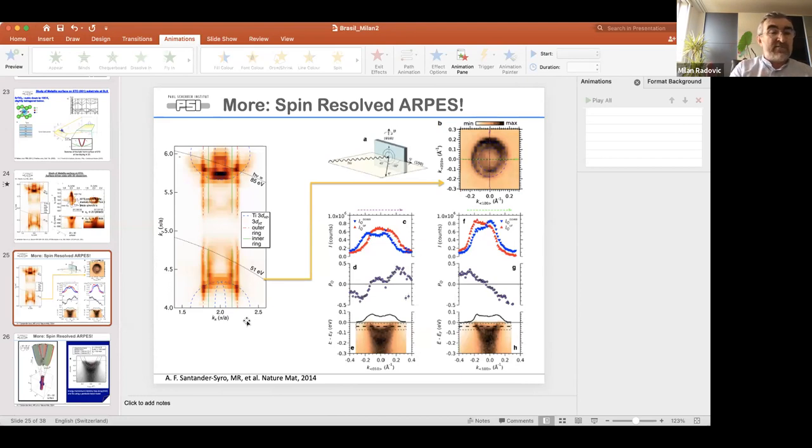For the STO and the films which we have, that can be achieved. For other systems, maybe it will be difficult. The second thing is, that means you have a large flux and long acquisition time, so beam damage can occur. That's the issue whenever you are working with that kind of spin detector, because measuring, for example, this spectrum which you see here takes 4 to 6 hours. And if this is not enough statistics, then you need once more. So to obtain the data which I just showed on one sample would take maybe 3 to 4 days, and the sample needs to survive. If it doesn't survive, then you need the next one, but maybe the next one is not the same anymore, et cetera.